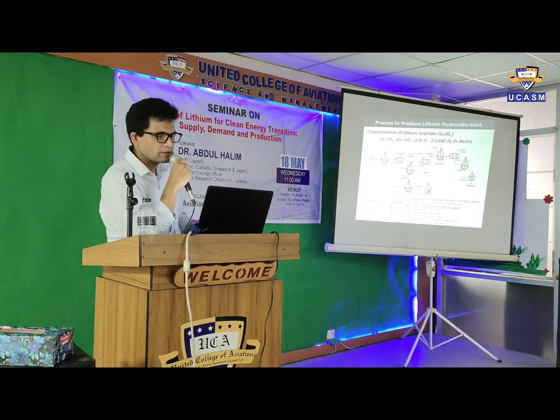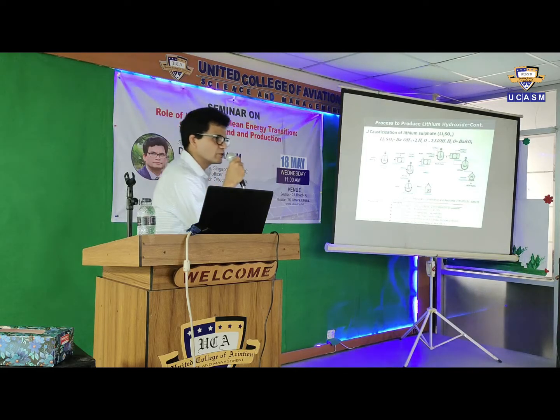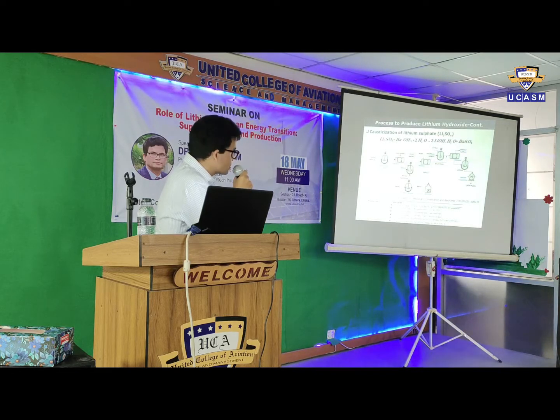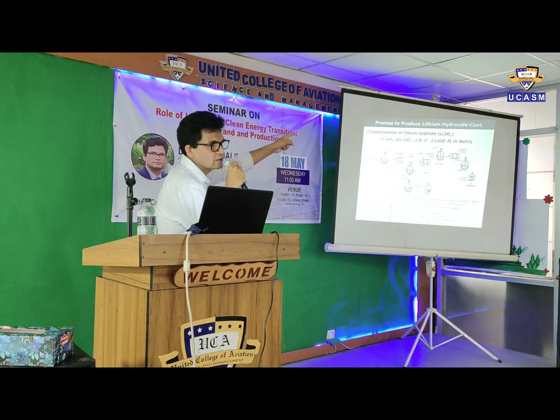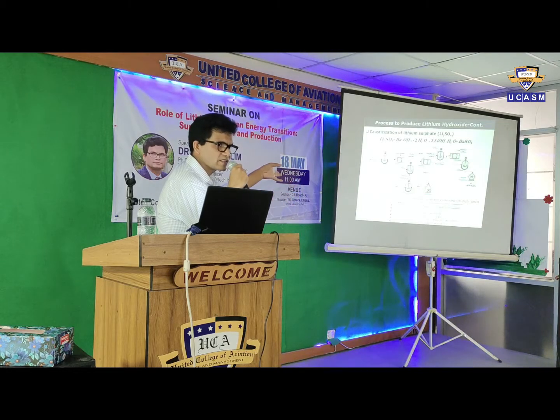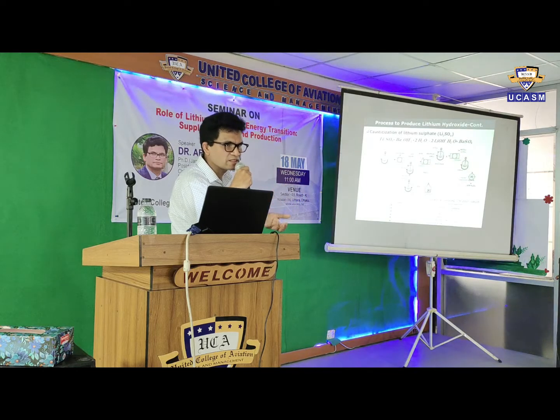Then finally they produce lithium hydroxide, but at the same time they produce barium sulfate. The barium sulfate, BaSO4, is the waste material. Then that barium sulfate can be heated at 1100 to 1300 degrees Celsius to get barium oxide. That barium oxide is recycled into the mainstream, so it is a closed loop. It is more efficient compared to the currently existing commercial process flowsheet, but this is only based on laboratory test work. This process should be run in a pilot plant, a demo plant, to generate the data.